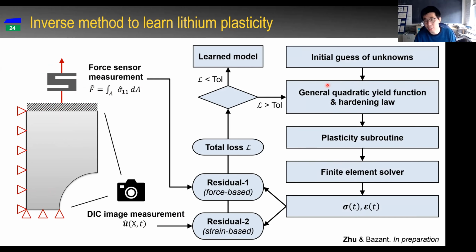We put in, for example, the general quadratic yield function and hardening law that we already know. We put the initial guess into it, and we design a plasticity subroutine and use an FE model to solve it. And we get the stress and strain field in the simulation. There are two residuals. One is force-based: we can compare the simulated force and the experimental force. More importantly, we can compare the strain-based residual so that we can minimize it and get the learned physics, learned mechanics. So now we have the algorithm.